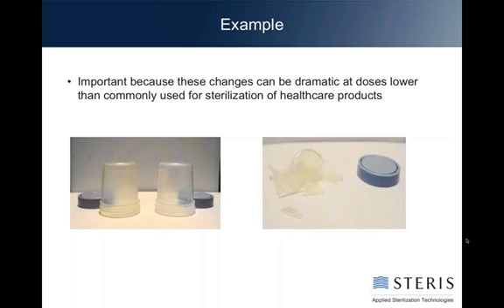Even at lower doses, it will at least make craze marks on it that will be points of weakness and will increase the likelihood of additional scission events in the presence of oxygen. So the changes can be dramatic. So you always want to keep track of, when you're seeing a color change, know it's there, know that it's not necessarily the main issue. There may be an underlying issue that's coming up behind it.